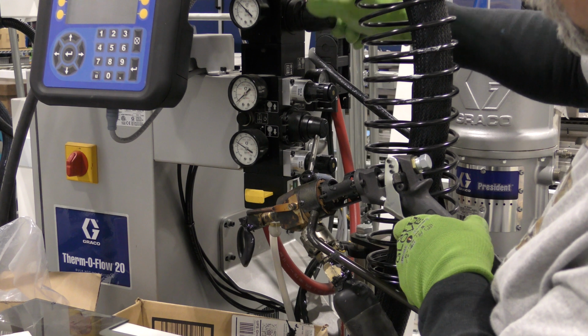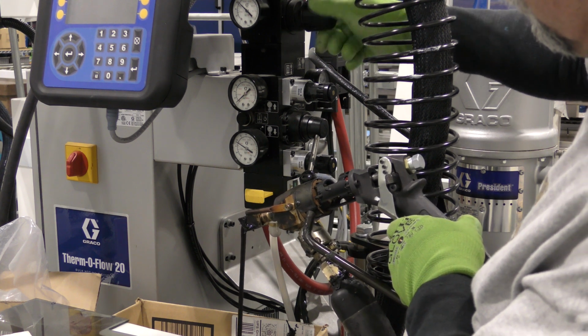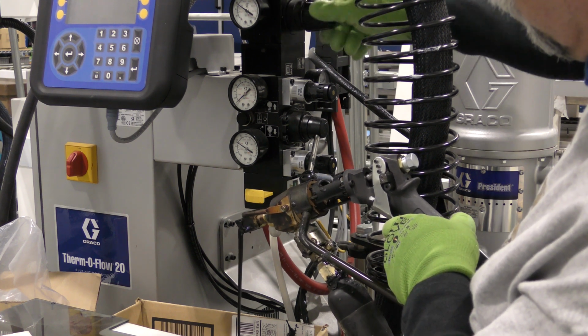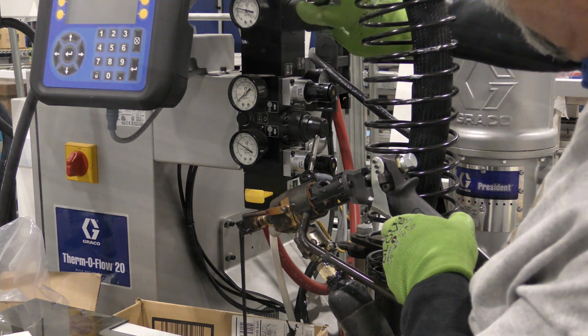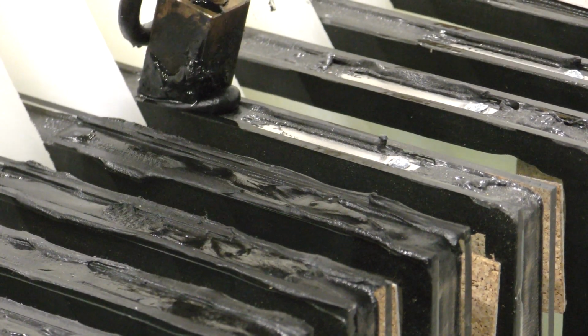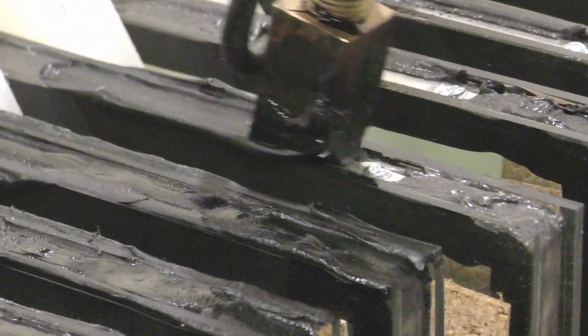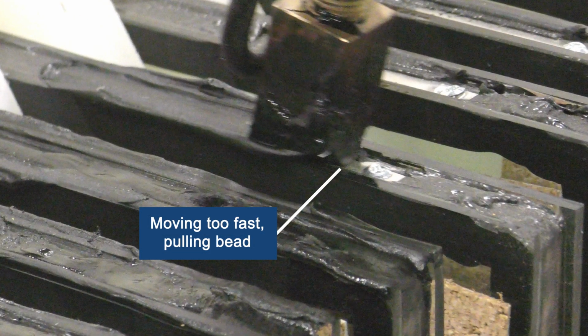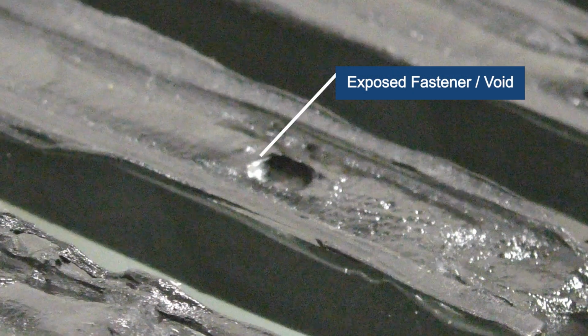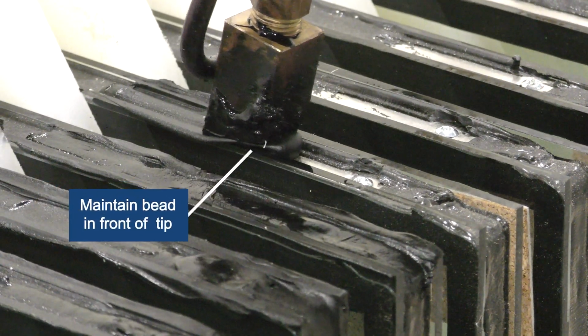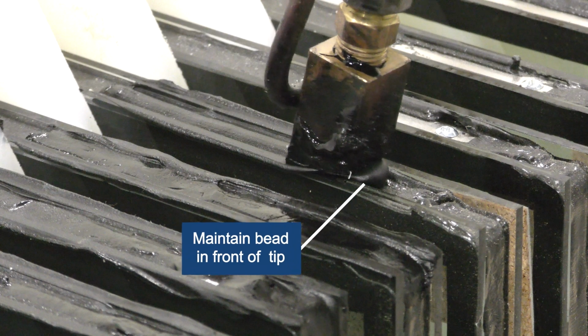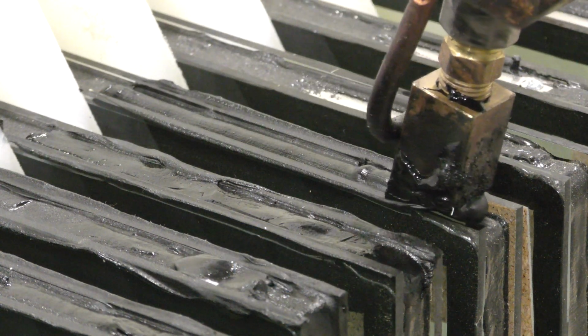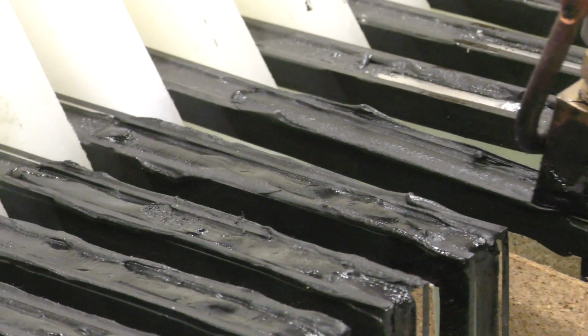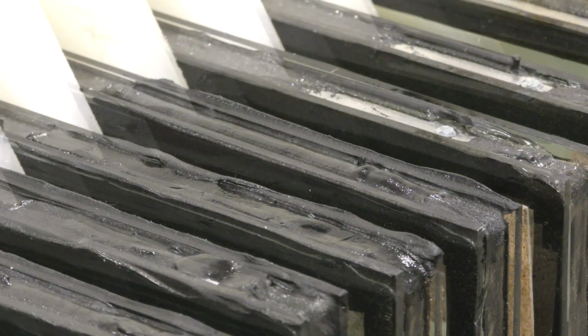Trial and error adjustments of the pump and gun flow characteristics will help the operator properly pace their movements. Proper directional movements and pace will help minimize sealant voids. There should be no spacer or fastener exposed. The key is to let the material push out from the front of the tip slightly and draw the bead towards the corner. Pulling the bead and moving too fast will leave voids.